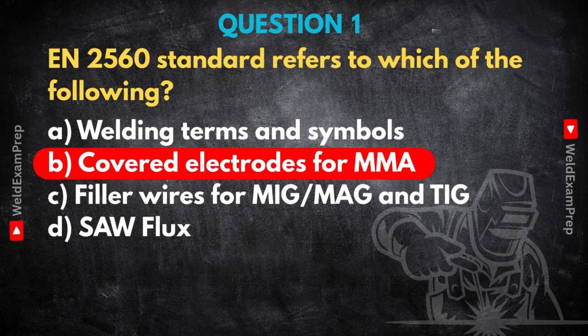But beyond just the exam, what's a real world situation where mixing up EN 2560 with, say, a TIG standard would actually cause a serious problem on a job? Oh, that's a really important point. Huge implications. Imagine you've got a WPS, a welding procedure specification, and it specifies an electrode under EN 2560, maybe like an E 42 3 B 32 H5, something specific. Now, if someone, maybe the inspector, maybe the fabricator, grabs the wrong standard, maybe they look at EN ISO 14341, which is for MIG wire, they could easily end up ordering or using the completely wrong consumable.